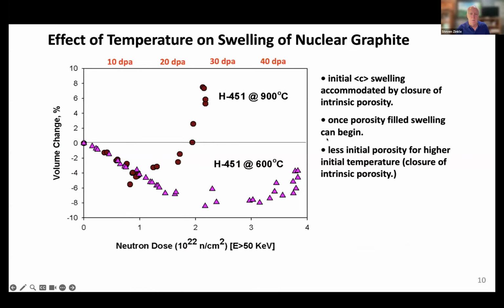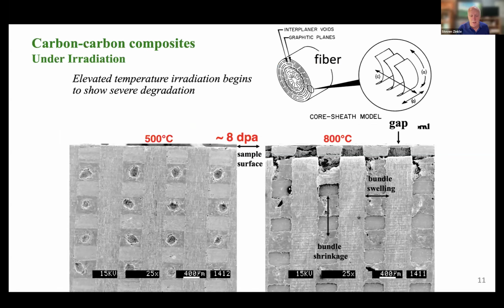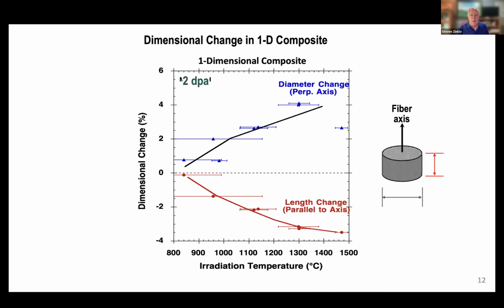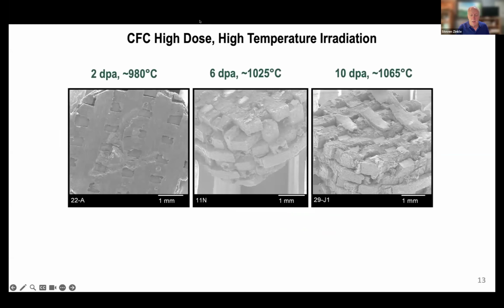From an engineering perspective, one can typically accommodate 5 to 10% of volumetric swelling in the material, but as you can see here, by the time we're reaching atomic displacement damage levels of 25 to 30 dpa, you would have unacceptably high volumetric swelling in the graphite. And this leads to significant cracking in the carbon-carbon composites that becomes progressively worse as you go up in temperatures, and leads to substantial degradation of the properties of the material, again, becoming increasingly worse as you go up to higher temperatures.